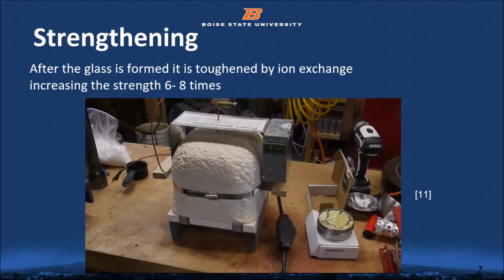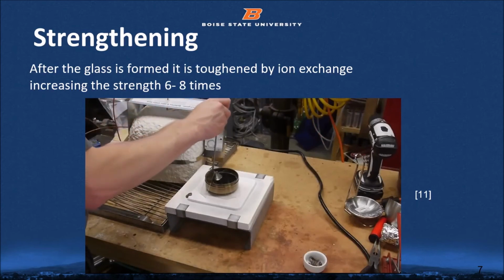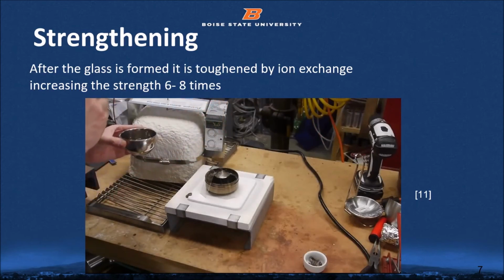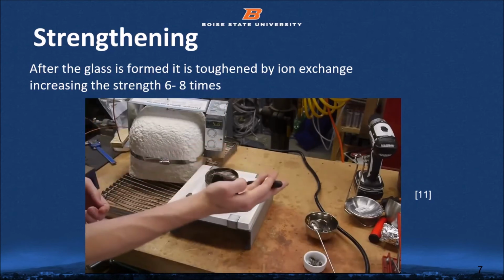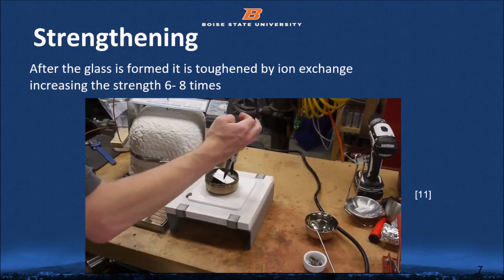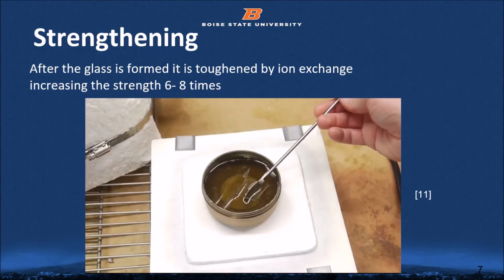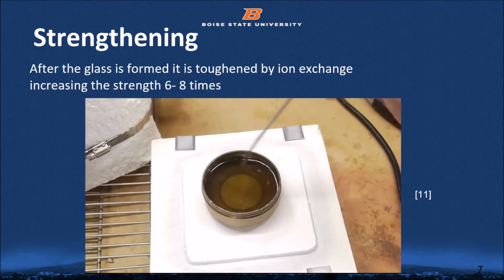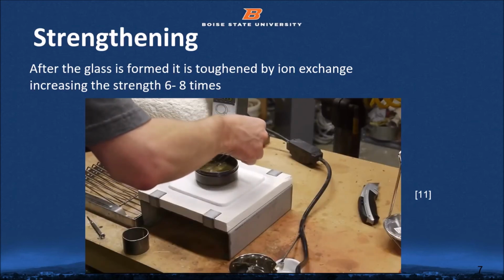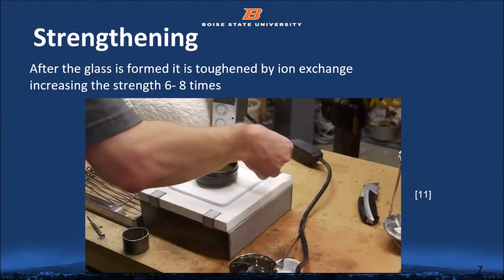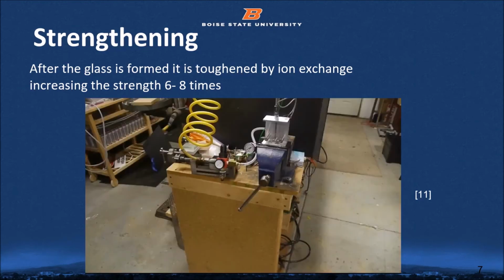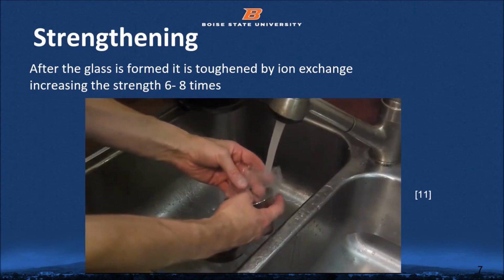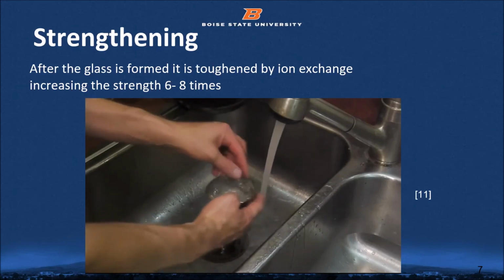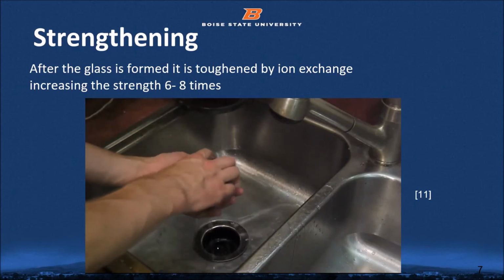After the kiln came up to temperature, I opened it up and noticed that the potassium nitrate had quite a few impurities floating on the surface, so I fished those off and then added the slides to the now molten potassium nitrate. Since the process was going pretty well, I also upped the temperature to 450 degrees. After 3 hours at that temperature, I fished the slides out and let them cool as slowly as possible, but I didn't do anything special like put them into a temperature-controlled chamber. I just put them out in air. After they cooled down naturally, I washed the slides off in tap water and then loaded them into the test rig and tested their strength.